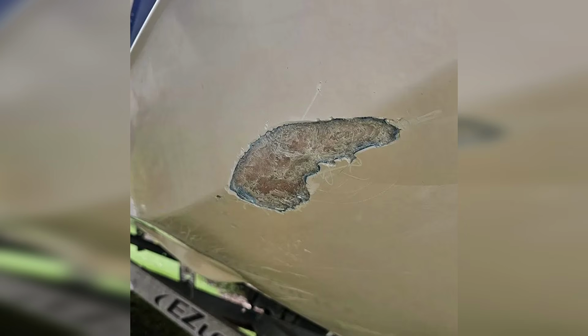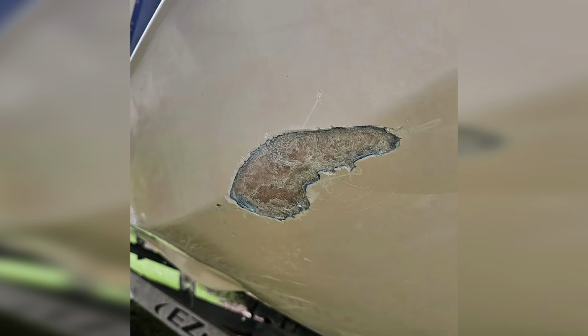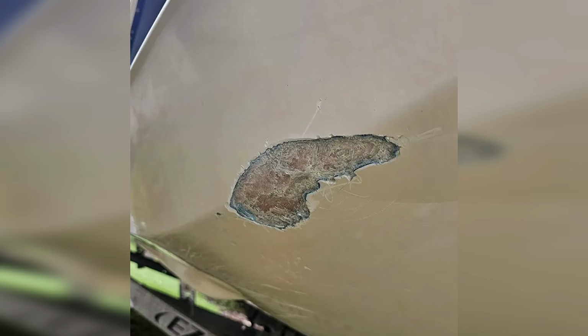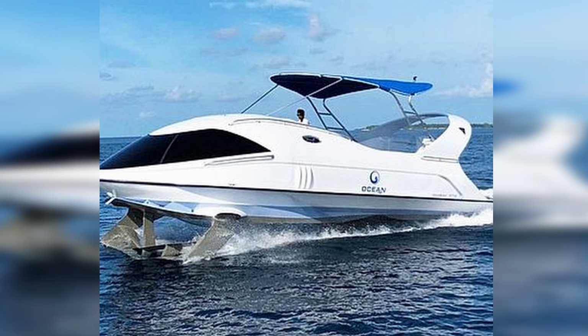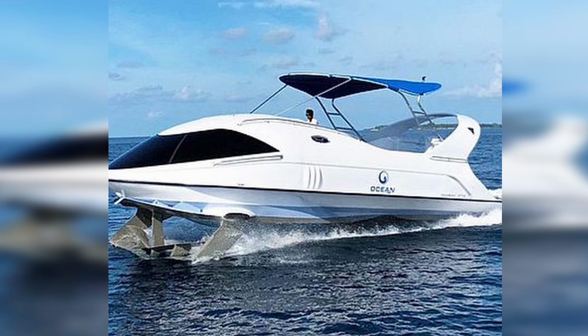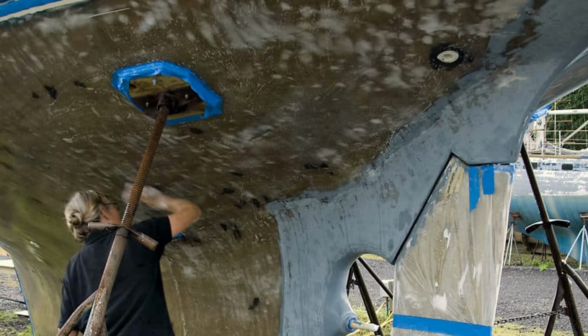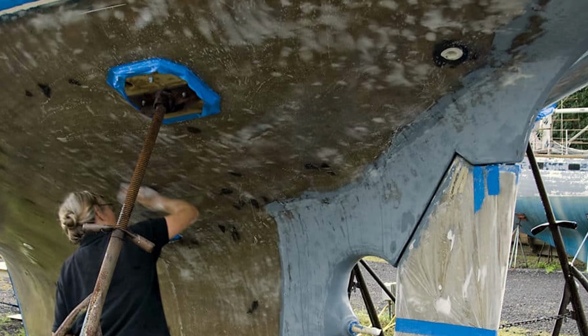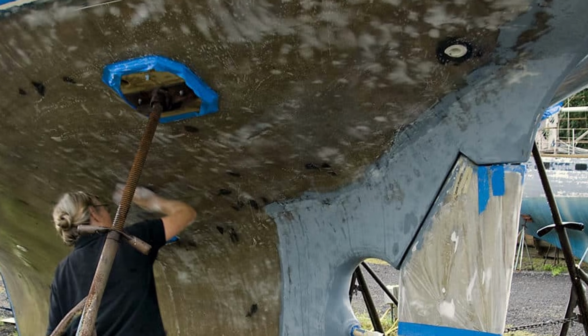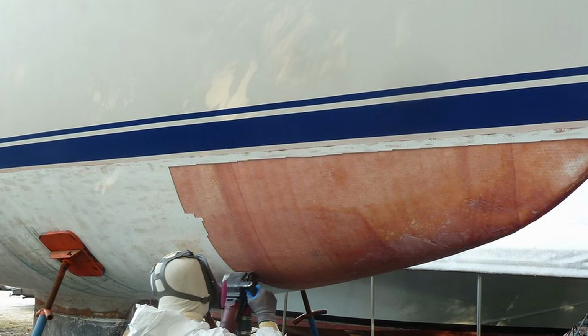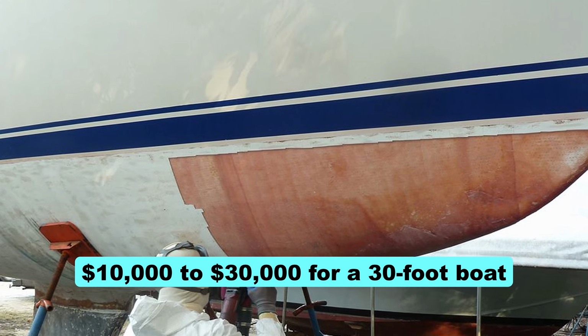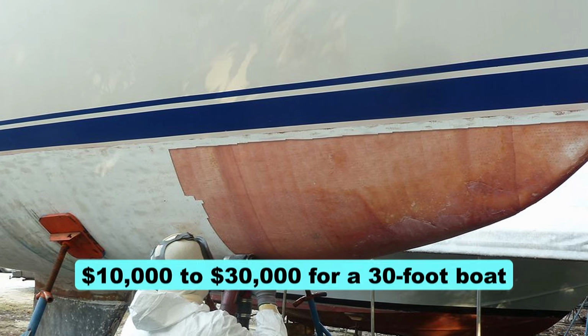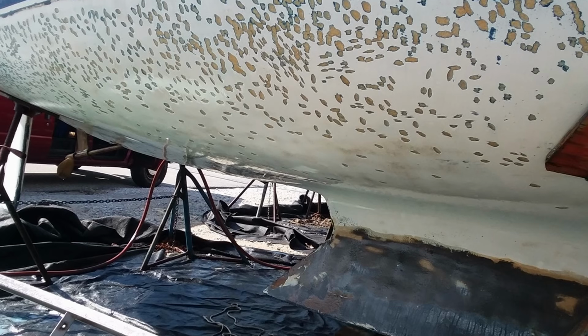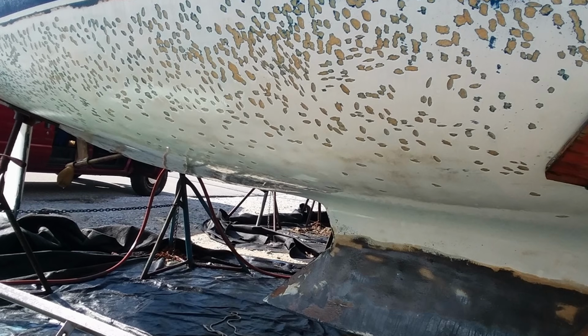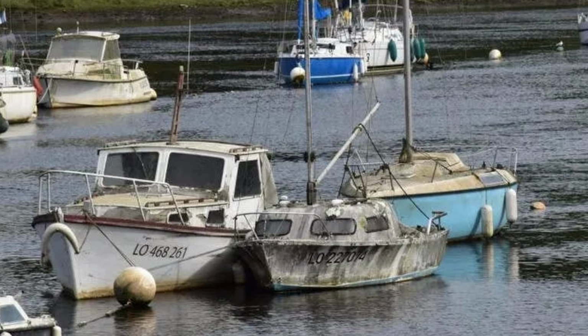This creates stress cracks at the joints where the hull meets the deck, around the keel and at bulkheads. A boat that was rigid and safe when new becomes soft and dangerous. The indestructible hull is quietly dissolving in the water it was designed to float on. And there's no real fix. You can grind off the blisters, dry out the laminate, and reseal it with epoxy. But that costs $10,000 to $30,000 for a 30-foot boat. And it's only a temporary patch. The water will find a way back in. The chemistry doesn't change.